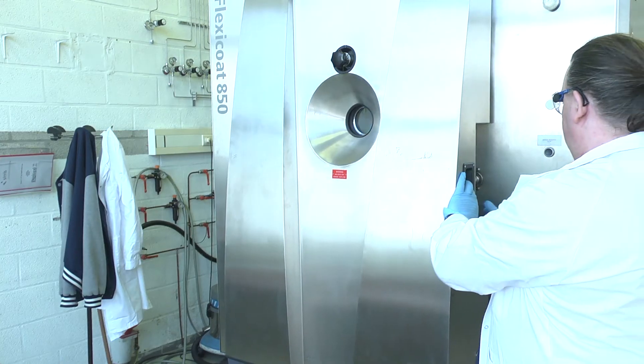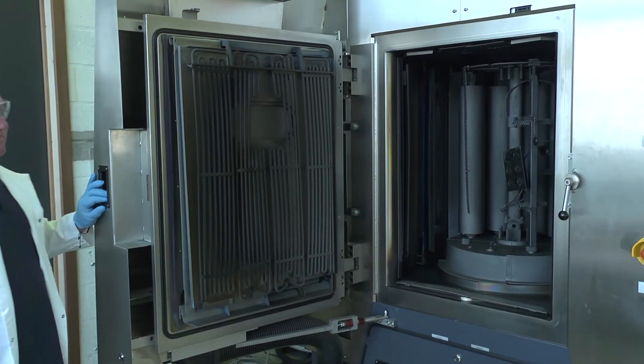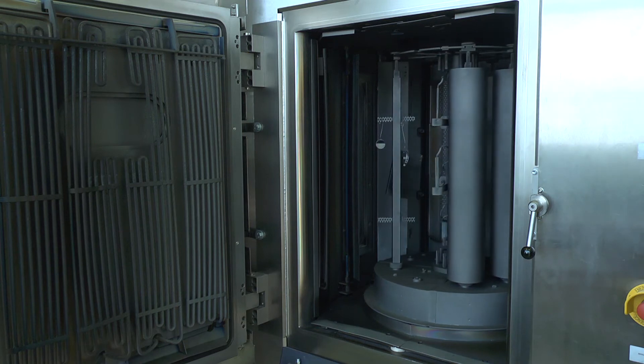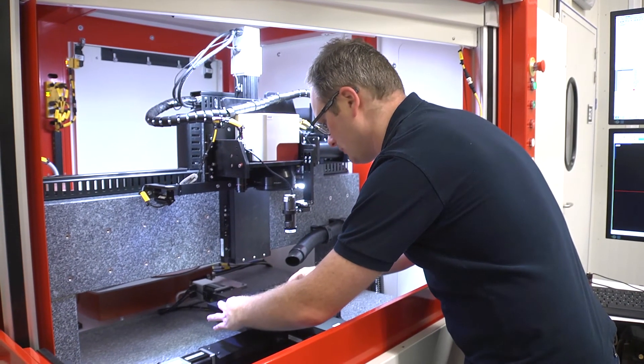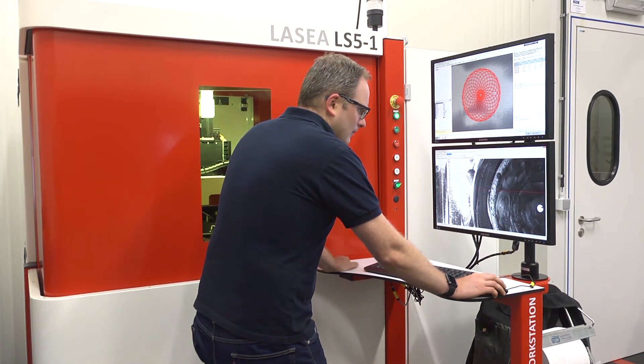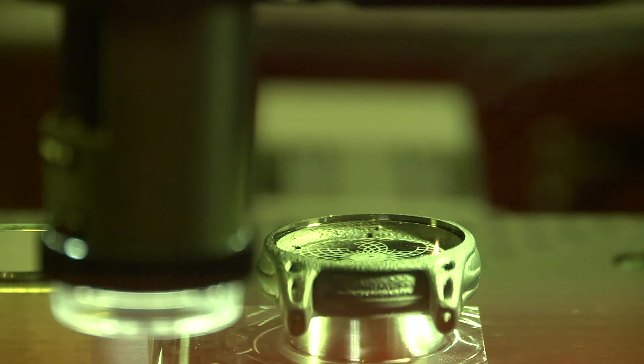In our demonstrator, we've selected a coating to add to the product using the PVD method. In this case, it is a chromium carbonitride coating which protects the watch from environmental influences. As a last step in the assembly, we further personalize the watch using a femtosecond laser. This laser erases the two top layers of the coating in order to reveal the chrome layer.